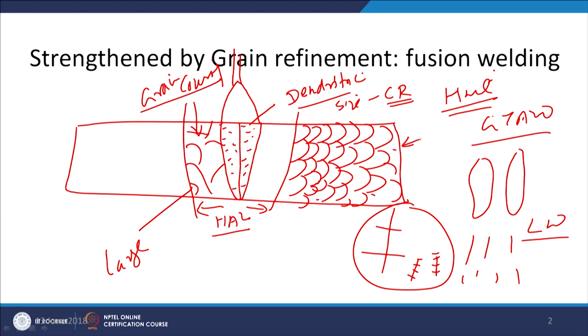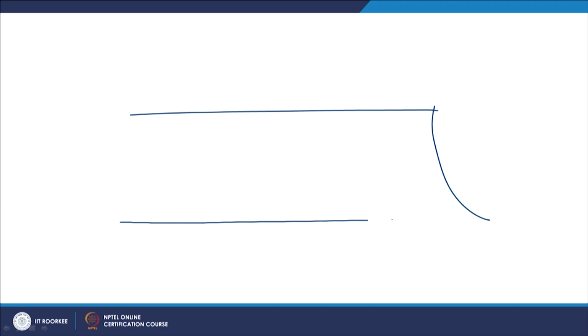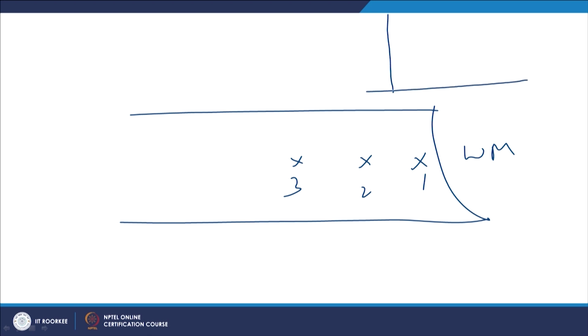So, it is very simple that whenever heat is supplied, the grains tend to grow, and that will depend upon the kind of weld thermal cycle experienced by the heat affected zone. So, if we take an example like this is the weld metal, this is one zone, this is another zone, with increasing distance from the fusion boundary. So, each zone will experience a different weld thermal cycle. Peak temperature will be maximum for location 1, somewhat lower for location 2 and further lower for location 3.